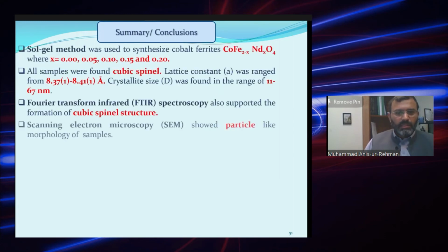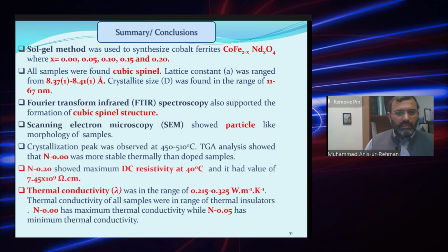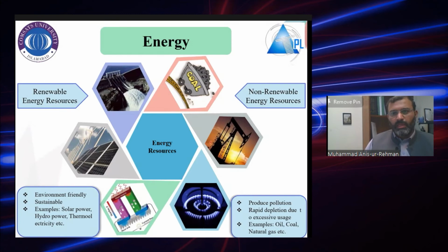Now coming to the summary of the second part, the sol-gel method was used for the preparation of the material. Cubic spinel structure was obtained, and in SEM we see the particle-like structures. The maximum resistivity was shown by the maximum doping concentration, and thermal conductivity was in the range of 0.215 to 0.325. So these materials could be used as thermal barrier coatings at higher temperatures also.